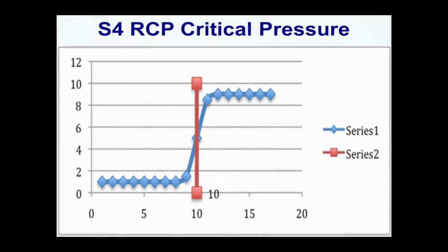This is what I mean by the critical pressure. This is simply a plot of the length of the crack versus pressure. At lower pressures, the crack arrests—it doesn't go a very long distance at all. At higher pressures, the crack propagates; it goes to the end of the pipe. In this case, this would be a 9-foot section of pipe, and it propagates all the way to the end.